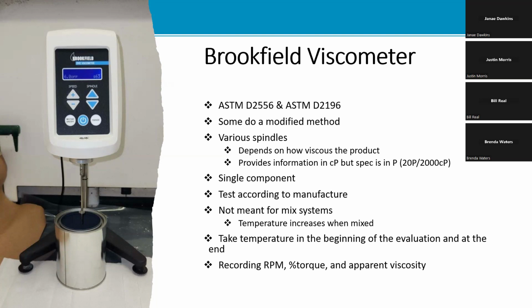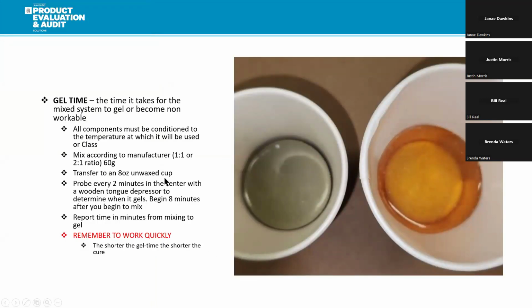So the next thing I want to talk to you about is gel time. Why is gel time important? Once the resin and the hardener are mixed, they begin to react and become thicker, making the material impossible to pour. So when you condition the materials that you're going to use, like a cup and a tongue depressor, these materials have to be conditioned according to the class that you're using the material in. Let's say, for example, you're going to use this product in a class A, and class A is for use below 4 degrees Celsius or 40 degrees Fahrenheit. So all your components must be conditioned to the specific temperature at which the product is to be used.